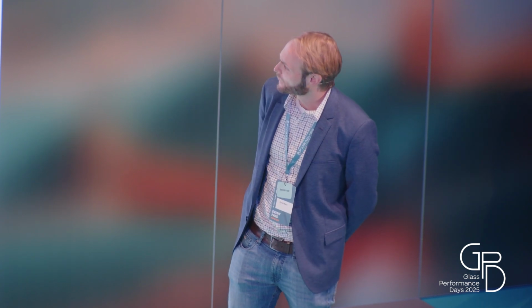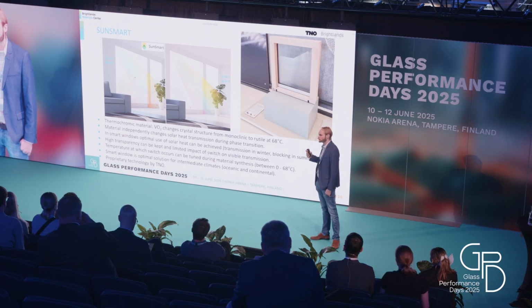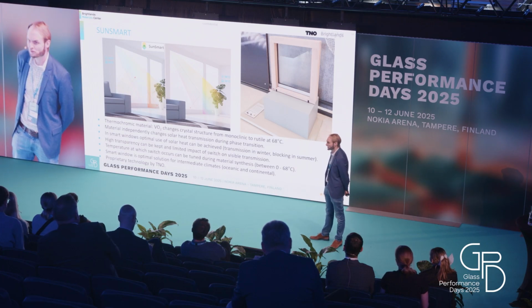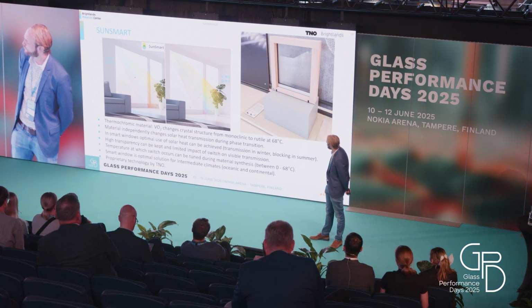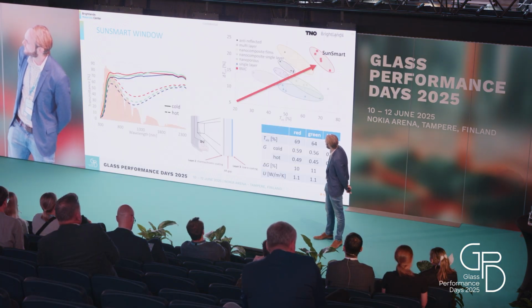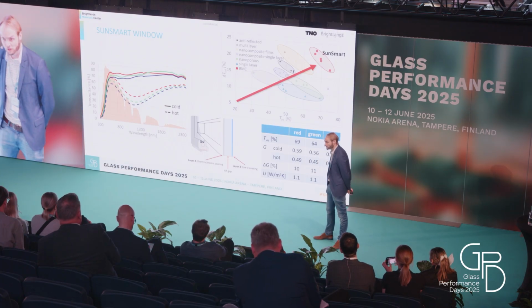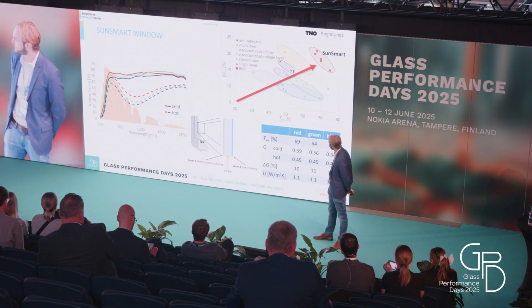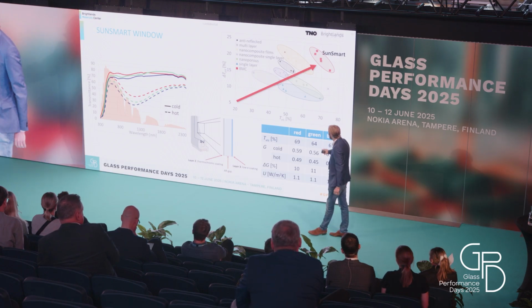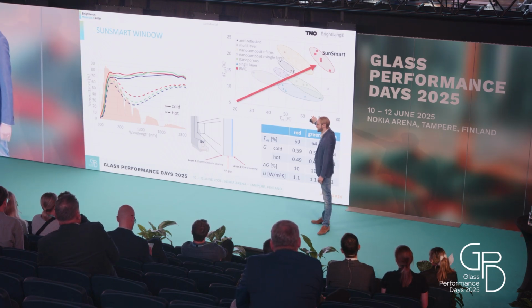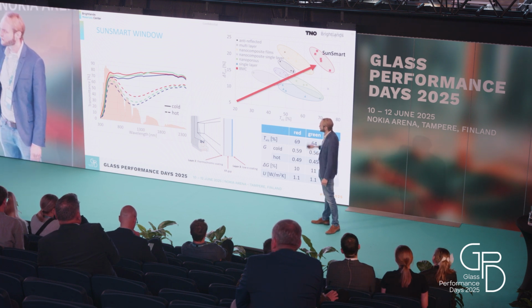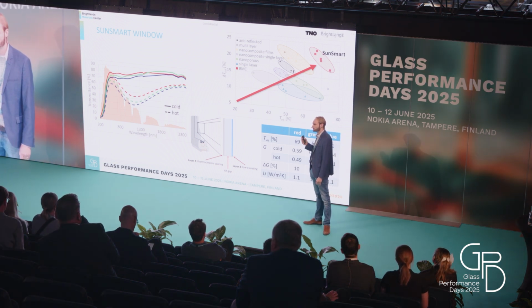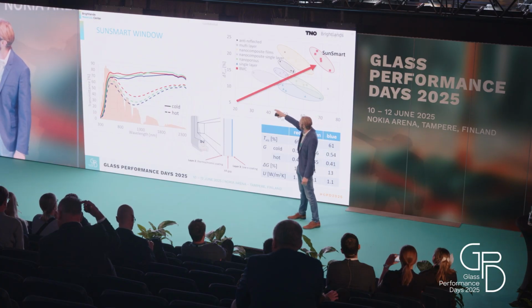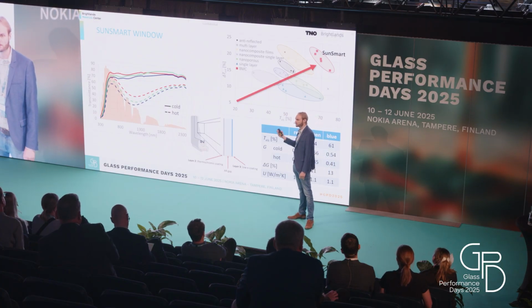So it's a completely transparent window as with your regular IGUs, but it modifies the infrared transmission through the window, depending on if you're in summer or in winter, to have the optimum G value and the optimum energy efficiency for your building. And the thermochromic material, vanadium dioxide, is not a new material, so it already has been worked on for 30 or 40 years. But what was always the challenge is to get optimized properties with a combination of a high transparency together with a high solar modulation. The solar modulation is the difference in total solar energy transmission between the cold and the hot state. And you want to have that as high as possible, which comes with a lot of functional material.